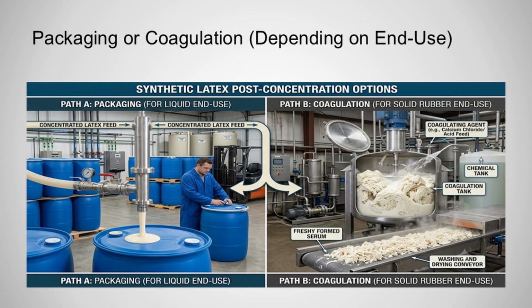packaging, or coagulation. For liquid latex application, such as adhesives, carpet backing, and dip gloves, the liquid emulsion is pumped directly into tanks, drums, or totes. For solid synthetic rubber, the latex is deliberately coagulated using acids or salts, washed to remove residual chemicals, dried with hot air, and pressed into bales of solid rubber.